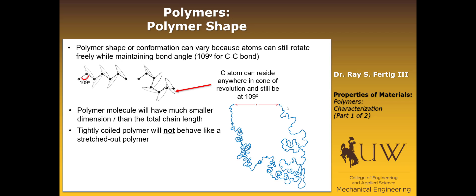Something else to be aware of, probably more as we go into next semester when we talk about mechanical behavior of polymers: if we have a polymer with really bulky side groups - not hydrogens, but benzene rings or something like that sticking off the side of the chain - the polymer can't move very easily to untangle or stretch in response to stress. Those bulky side groups actually block each other. That's a phenomenon we call steric hindrance. Those are the important features you need to be aware of with respect to polymer shape.